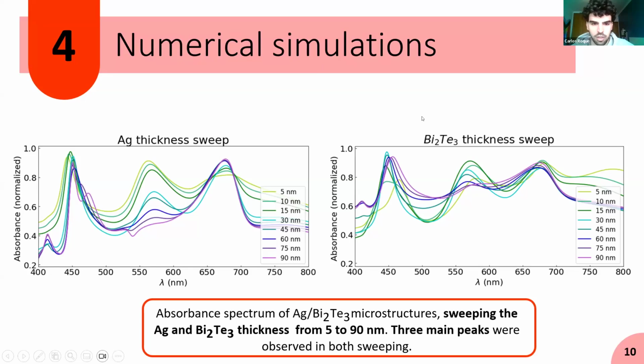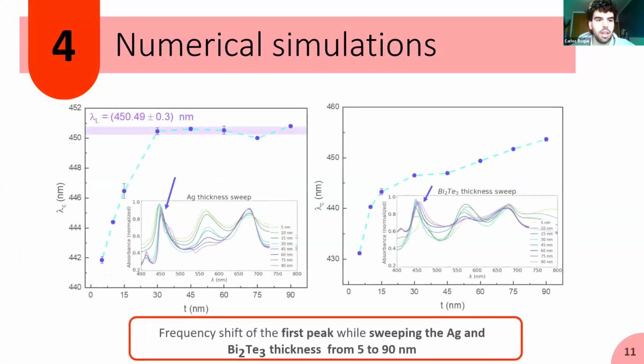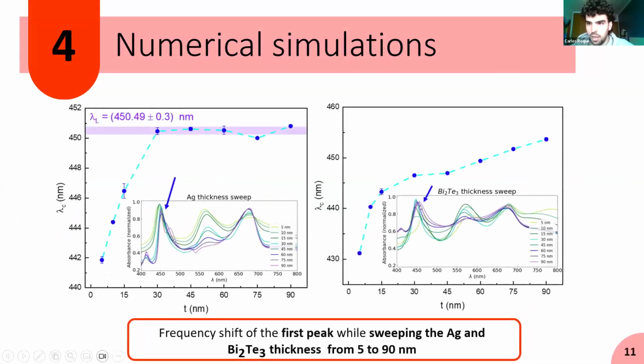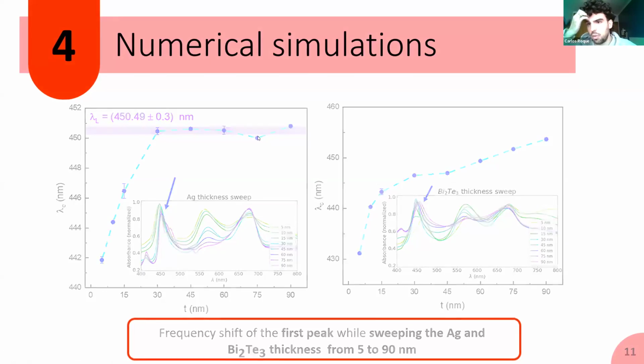So we studied this frequency shifting for both of the layers. And as you can see, they are rather different, and this is expected because optically these materials are rather different, so different behaviors are also expected. And then focusing on the silver one, you can see that the wavelength of excitation increases for increasing thickness of the silver up to a thickness of 30 nanometers. Above this thickness, we overcome the skin depth of the silver for this wavelength, so the wavelength stays fixed. And this feature is also observed for the second peak.